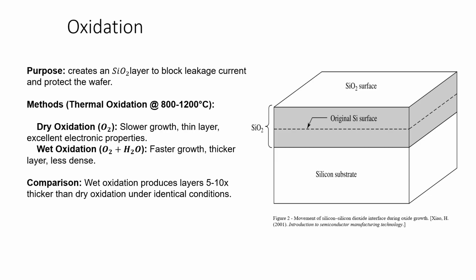We use two types. Dry oxidation uses pure oxygen to grow a thin layer with excellent electronic properties, and wet oxidation uses oxygen and vapor, which grows the layer 5 to 10 times faster, though it is less dense than the dry method.